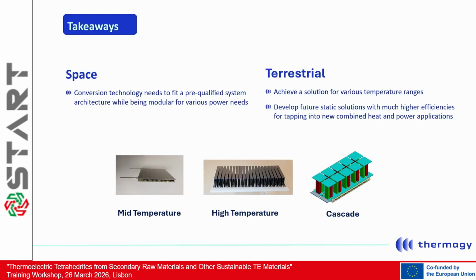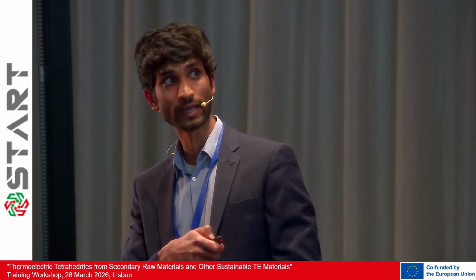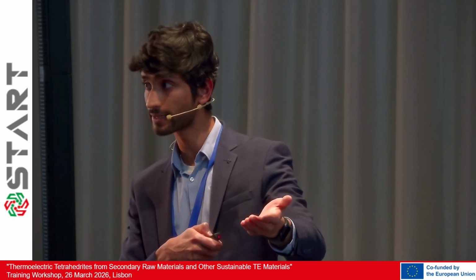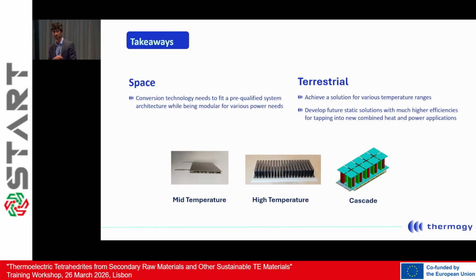A few key takeaways, both from the space as well as our terrestrial end users, is that we want to achieve a solution for the various temperature ranges. So it not only should operate well within the delta T, but also be something that we can cascade together for even higher efficiencies. Within the START project, the aim was to get to something which can operate at 300 degrees centigrade with a stable material, and that is the quest that we have in this project. While in the high temperature, we have been working with silicon germanium materials, and that's the architecture I was showing you previously. So in the future, we want to develop such static solutions with high efficiencies of 9 to 10%